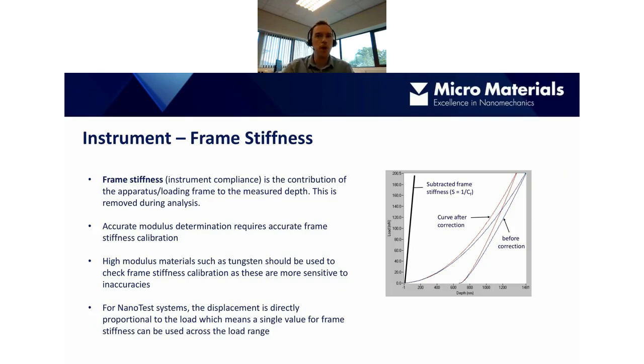Okay, so frame stiffness is another important factor. This is the contribution of the loading frame of the system to the measured depth. So you can see here, if we were to plot this contribution of the instrument, this frame compliance or frame stiffness, on the same plot as the indentation curves, we'd see essentially a linear straight line here. So during the analysis, the frame compliance is removed from the raw data. You can see here this is the indentation curve before the compliance is removed, and then this is what you might call the true sample response after this has been removed.